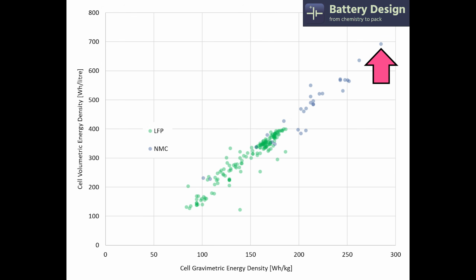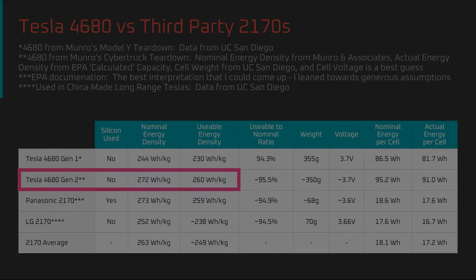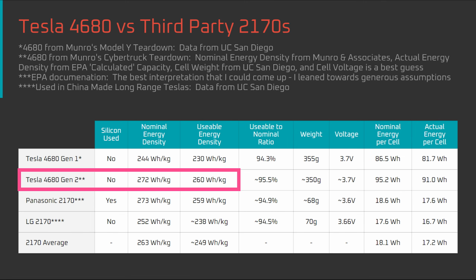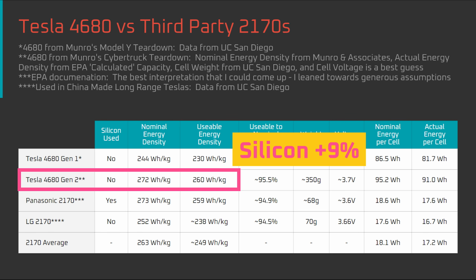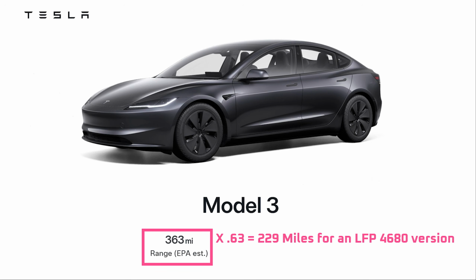Third, my understanding is that the NMC cell used as a comparison in this image from BatteryDesign.net contains silicon. That's as opposed to the Generation 2 4680, which didn't use silicon, meaning it was handicapped compared to the prismatic cell comparison. Let's say the silicon is worth about a 9% energy density increase. If we adjust for all those factors, it means we could likely add about 15% to the 229-mile range of an LFP 4680 Model 3 to reach 263 miles of range.